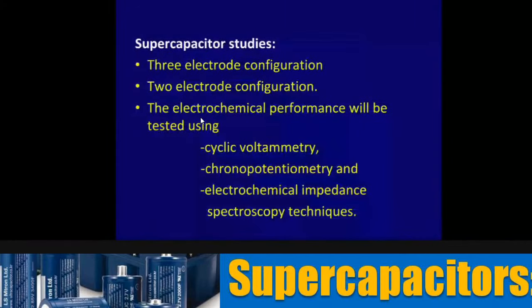And this electrochemical performance will be tested through 3 important measurements. One is called the cyclic voltammetry. In cyclic voltammetry, what is done is, the potential employed is slowly increased at a predetermined rate, and the resultant current is measured. So normally this is done in a cyclic manner, like we will go say from 0 to 1.2 volt, and in the reverse direction we will go from plus 1.2 to 0, so that we understand the way charges are given to the supercapacitors and charges are extracted from the supercapacitor. Because when you go from 0 to 1.2, it is a case of charging of the device. And when you get back, you are trying to recover the charges.